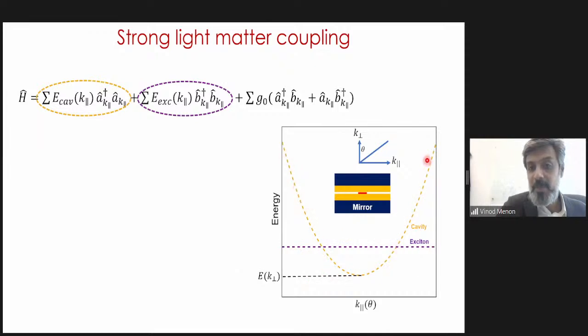dashed line here. The exciton is almost a flat line. The reason it's a flat line and doesn't have dispersion, while you do know from your Kittel, your textbook, that the excitons also should have dispersion, the reason you don't have a dispersion is because within the wave vectors we are talking about, this is so much more massive than the photon that it will be almost a flat line. You need to go to very large wave vectors before you start seeing any curvature of the exciton. So within the wave vectors where you want to resolve the cavity dispersion, the exciton can be treated as a flat dispersion because it's so much more massive.